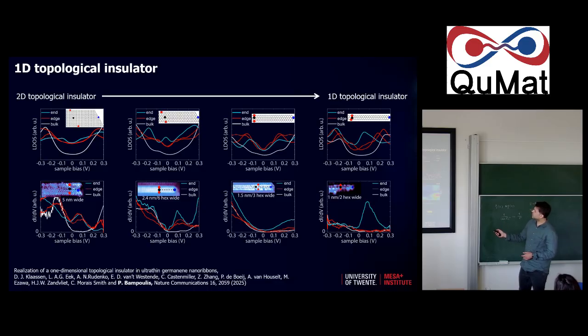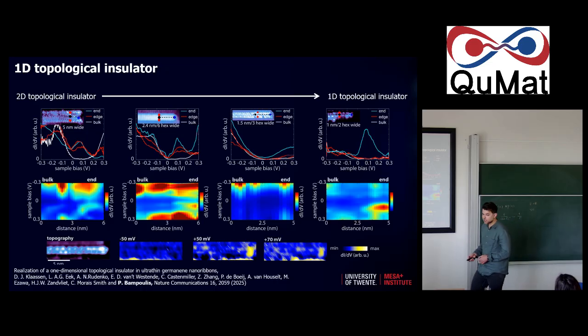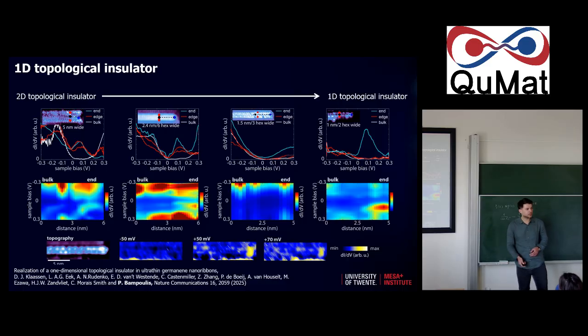All right. So here I give you a few more line spectroscopy maps just to give you a complete picture. Over here you still see your end state. Here there is no end state, so bulk and end look the same, about 3 hexagons wide. And at 2 hexagons wide, you have it very, very sharply localized. You can even map a 2 hexagon wide nanoribbon, and you see that at these energies where you expect your end state, you have it exactly localized at the end of the nanoribbon. So what we think we have is a nice example of a transition from a 2D topological system to a 1D topological insulator with symmetry protected zero-dimensional end states.